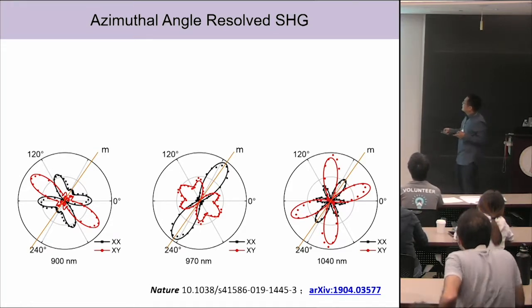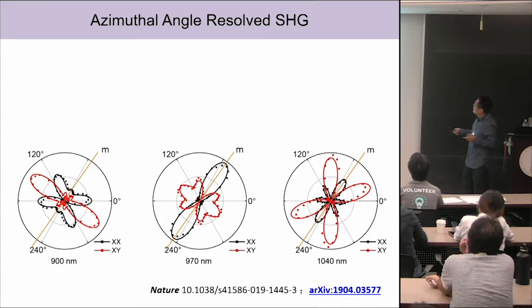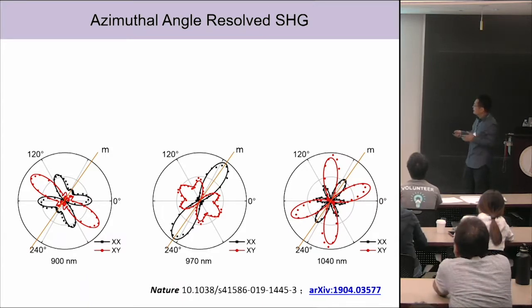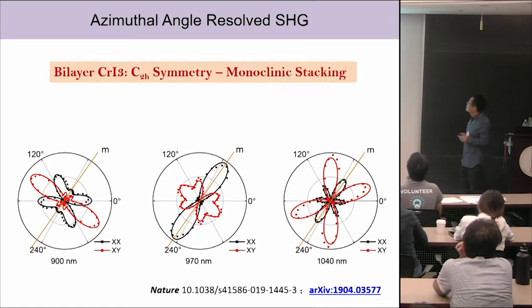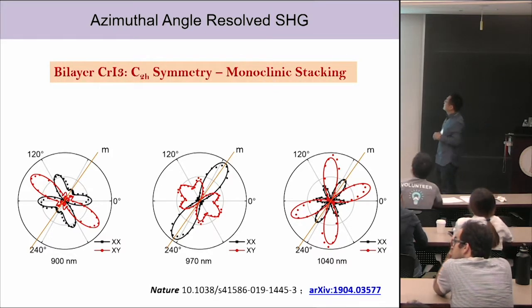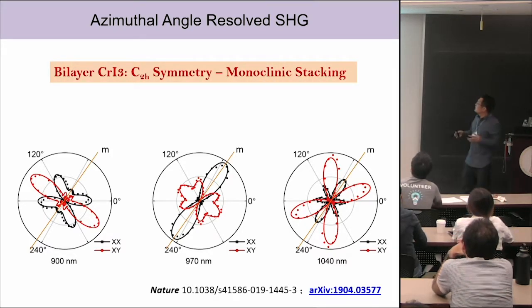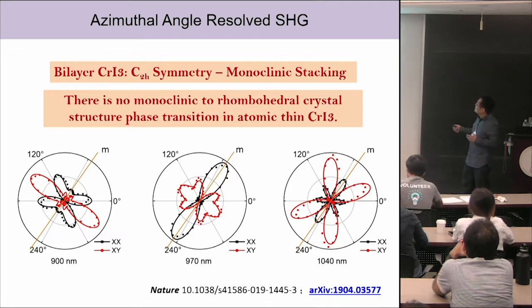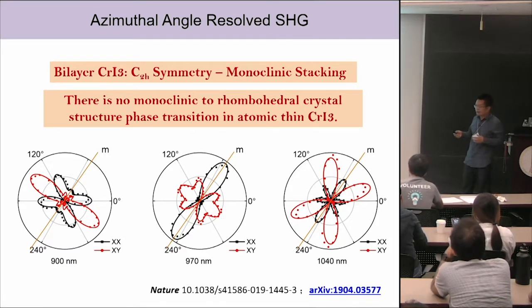We can also fit the data really well with C2h symmetry, all these 3 samples, all these 3 different patterns. So the conclusion is, for bilayer chromium triiodide, it has this C2h symmetry and it has monoclinic stacking. And there's no monoclinic to rhombohedral crystal structure phase transition in atomically thin chromium triiodide. Okay?